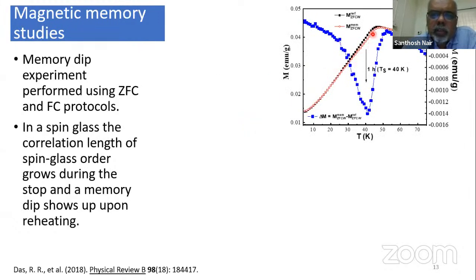So what we do is take the magnetization curve in a zero field cooled, cool it all the way down, and use that as a reference curve, and take the warm-up curve, and then you have a cooling down where at some temperature you have a waiting period. So for 1 hour, you keep the system kept at a particular temperature. Here we have taken 40 Kelvin, and then cool it down, and then you warm it up again. So the difference between the two warming up curves shows there is a dip at the temperature we kept it for, we halted the system. So that says that the system remembers where it was halted.